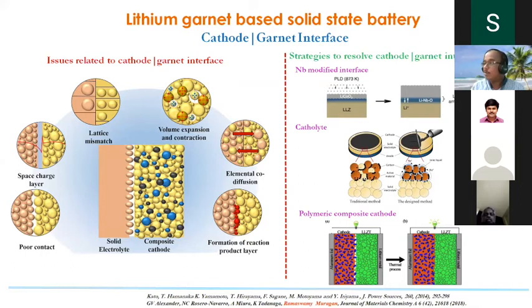And polymeric composite is another example. Put the mild polymer at the interface with the cathode and the lithium garnets and just go for a thermal process and make a perfect bonding. So at present, people are working with the catholytes. By the way, they are able to improve contacts and really they are improving the cycling efficiency.